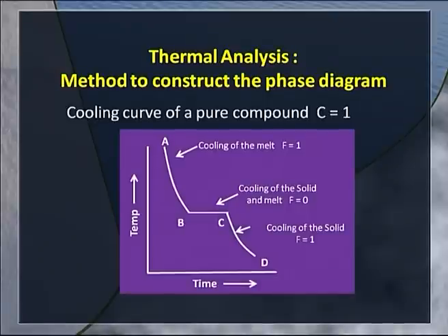How to construct such phase diagrams? We have a thermal analysis method in which we study the cooling curves. In this case, we can look at the cooling curve for a pure compound. We take it to the molten state and as a function of time measure the temperature.